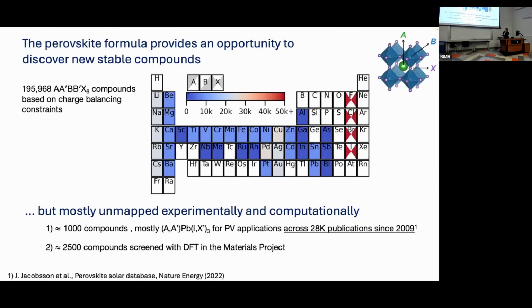If you look at the Materials Project, which catalogs a lot of computational data, then you can see that there's about 2,500 compounds that have been published there. So we know about the inorganic space. This is experimental compounds. That's because of this ambitious work done at the Helmholtz-Zentrum, where Jesper Jacobsen led a team to go through the field and actually by hand catalog what has been published in the literature. So this is a really wonderful database if you're interested in perovskites.